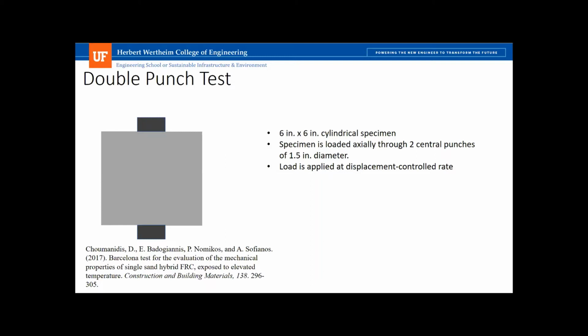It's called the double punch test or Barcelona test. It was originally developed in the 1970s as a test to measure plain concrete tensile properties, but it was adapted recently for ultra high performance concrete or fiber reinforced concrete by a group in Barcelona, Spain. In this case, you have a concrete sample where you have 2 steel punches that you place on the top of the concrete sample.